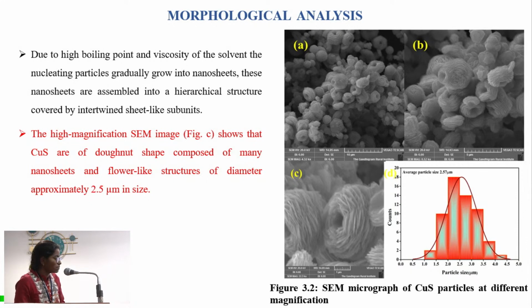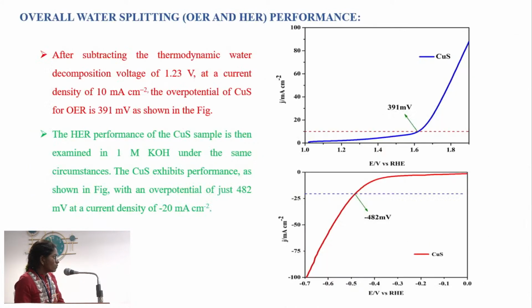Through the histogram I have confirmed the particle size; picture C shows the magnified image. A particle diameter of 2.5 micrometers has been grown. I have employed that electrode material for water splitting as a bifunctional catalyst for the hydrogen evolution reaction and oxygen evolution reaction. For hydrogen evolution reaction, I have obtained an overpotential of 480 millivolt at 20 milliampere per centimeter square. And for oxygen evolution reaction, I have obtained 391 millivolt at 10 milliampere per centimeter square. We can further improve the performance by adding composites like carbon materials such as carbon nanotubes or carbon fibers. For the pure material, I have obtained low overpotentials for both oxygen evolution and hydrogen evolution.